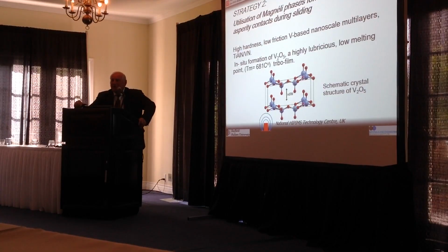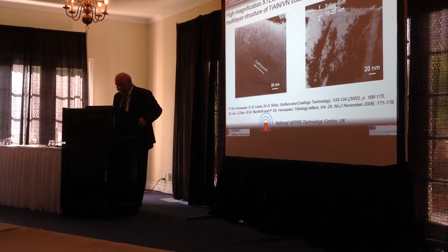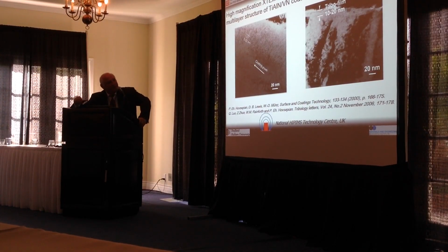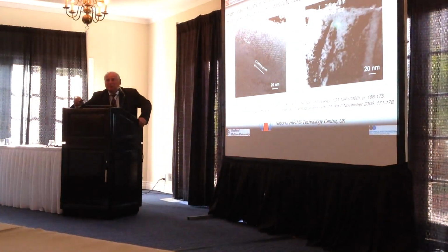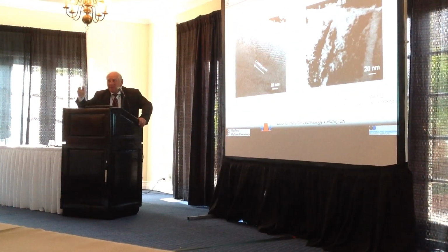With vanadium pentoxide, you also have the benefit of a very low melting point. So this is how the structure looks. You form a tribofilm, 10, 20 nanometers. And if you investigate by Raman what the phase composition of this film is, it will be vanadium pentoxide.